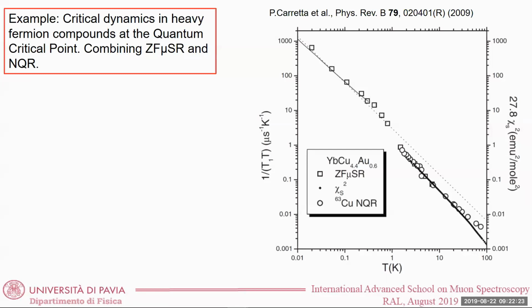This is in zero field. We did zero field µSR, to study the longitudinal relaxation rate, the zero field relaxation rate here. And we saw this, let's say, divergence of the relaxation rate to very high values. So this could be done only thanks to the fact that µSR allows you to estimate very fast relaxation rates. And let's say this is a behavior one expects close to a quantum critical point for this heavy fermion compound.